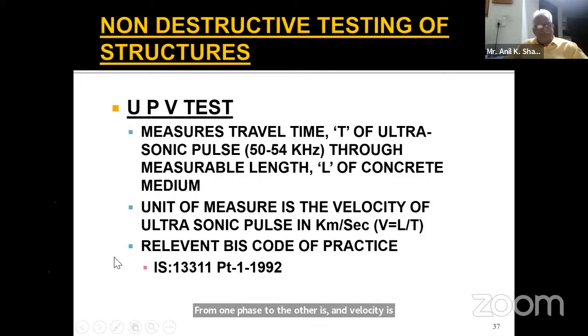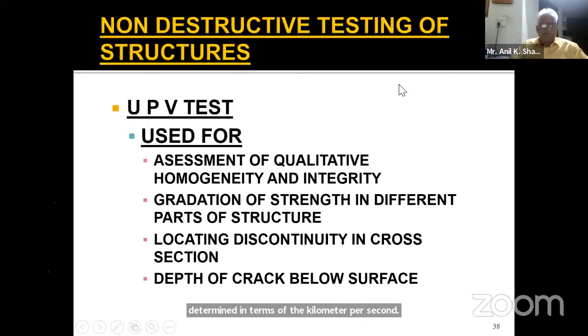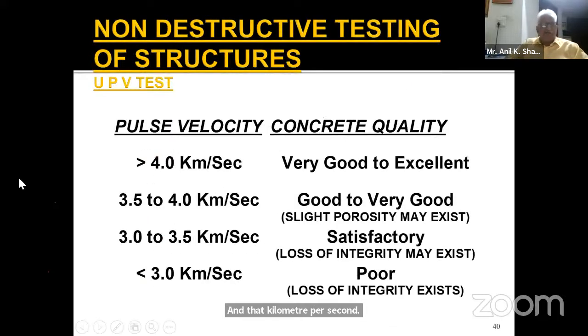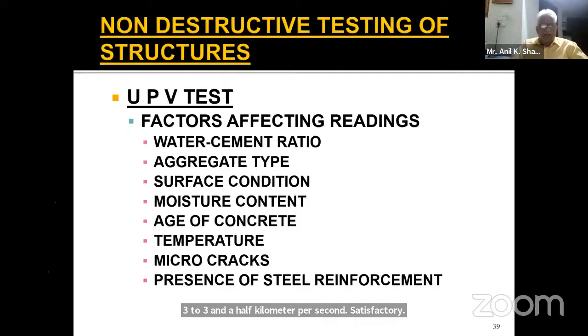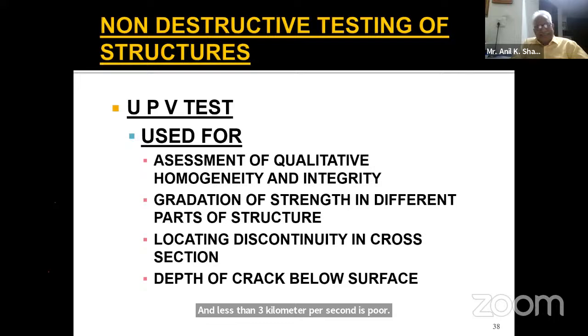That velocity is related to the quality of the concrete. For example, if the ultrasonic pulse velocity is more than 4 km per second, quality is considered very good or excellent. 3.5 to 4 km per second is good to very good, 3 to 3.5 km per second is satisfactory, and less than 3 km per second is poor. The test is used for assessment of qualitative homogeneity and integrity of the concrete. It is used for gradation of strength in different parts of the structure.